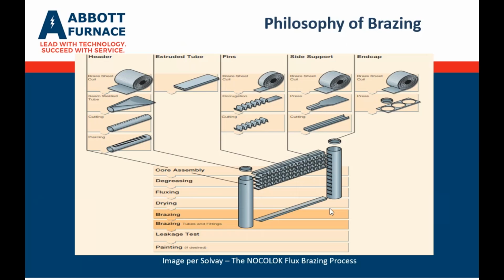And we'll talk about some complexities of these channels, microchannels that create some voids and openings inside. Then you have your fins that are brazed together to the tubes. You can have various side supports, end caps, spigots. There are all kinds of things that can be added, whether it's brazed or post-braze applications. But you take all of the parts, you put them together in an assembly with some kind of a fixture to hold them in place. And then we start going through the process of cleaning or degreasing, fluxing, drying, brazing, and then any testing, where there's pressure test, leak test, and then finally, in some cases, people are painting them for cosmetic appearances.